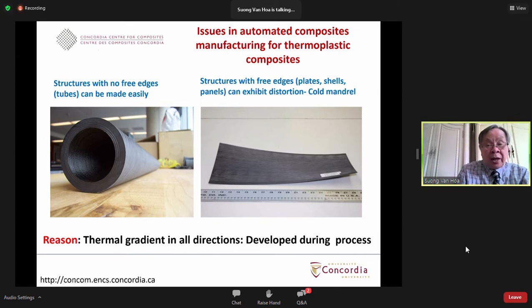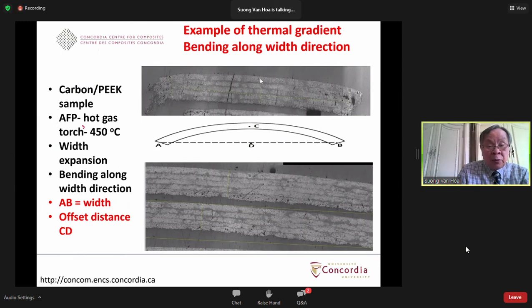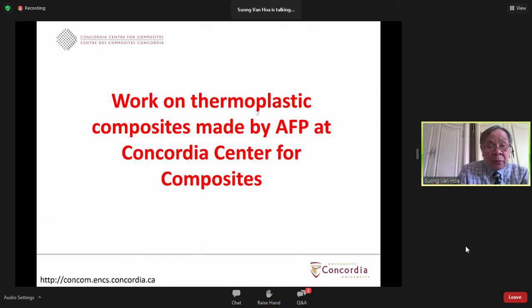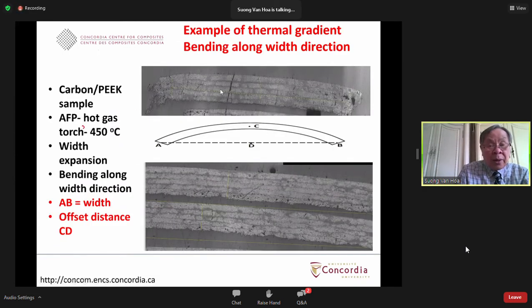Now, one example of thermal gradient is that we find the laminates also tend to bend. This one here shows a section of the thermoplastic composite along the width. The distance from left to right here is about 1/4 of an inch. What we find is that during the process, the width becomes longer and the thickness becomes thinner, which is expected. But what else is observed is that it also tends to bend like this.